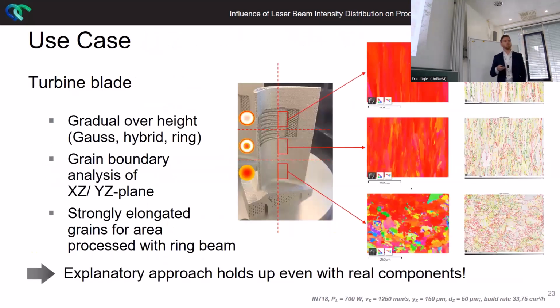Yeah, what we then thought is, is it only possible for simple geometries, or is it even possible with realistic components? And as you can see here, it is. We printed a turbine blade out of this nickel-based superalloy and ran another EBSD analysis. And what we did is to print at different heights, different indices: index 0 on the bottom, index 3 in the middle, and index 6 on the top. And those trends were confirmed here again. So it's reproducible, with irregularly oriented grains here for index 0, whereas the texture is really sharp for the sample of index 6 and the area on the other side.